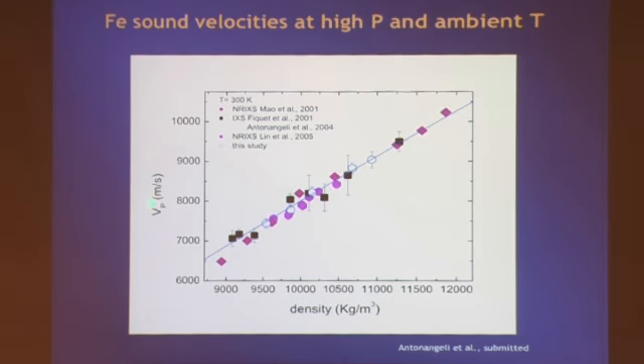Okay, here I'm plotting the compressional velocity VP as a function of density as obtained by different techniques. Luckily here you can see all the things that were not possible to show before. From the original paper, Antonangeli's measurement, by Mao and co-workers, Fiquet, and following measurements done by these two techniques over the last 10 years. Once plotted as a function of density, and once used for the analysis of the data a suitable non-hydrostatic equation of state, all the data plot overall on a straight line and compare overall favorably. Maybe a partial exception can be this point that was the one driving the extrapolation up a bit. But anyhow, we can feel confident of this result. And this open symbol is a measurement we took recently this year, which still stays there. So positive, we have a reference value for iron, and we can see what happens when alloying nickel and silicon.